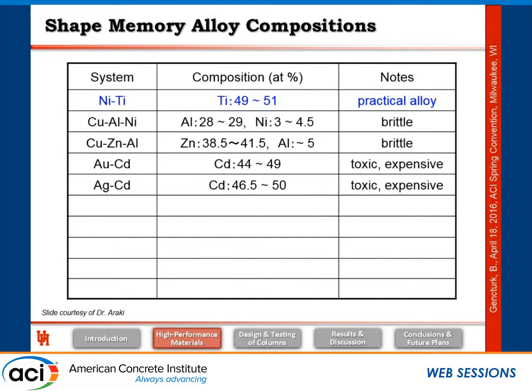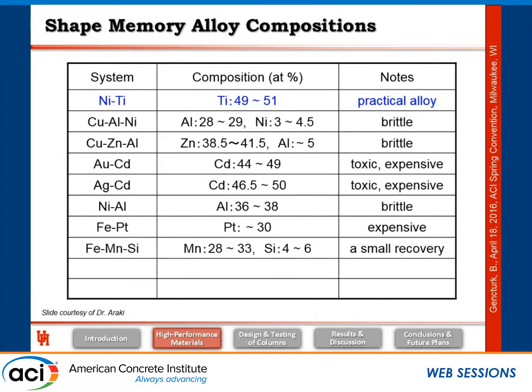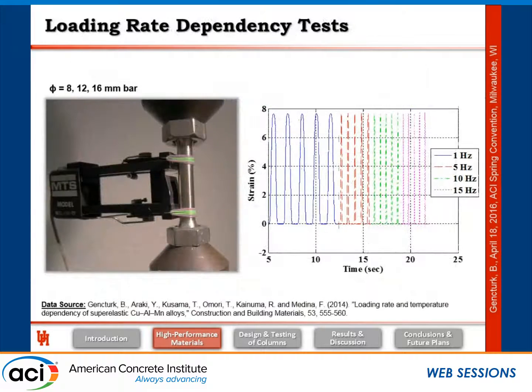Even if they're not expensive, they are toxic. There are nickel-aluminum ones. They are brittle. There are some iron-based ones. They're either too expensive or they only show a small recovery. And then the alloy that we are using for this research is this copper-aluminum-manganese alloy, which is considerably cheaper than the nickel-titanium counterpart. Because this material is still not very well characterized, we have done some testing on it. I'm going to present some of the results here.